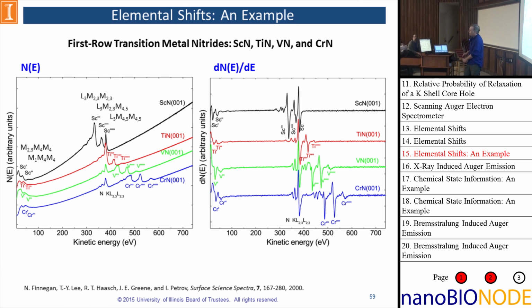Traditionally, Auger spectra can be presented two different ways. The first way is the N of E mode, where you'll see that the lines are fairly small on a linear and intense background. And so in that case, we can also do a first derivative of the spectra. That way we enhance the signal quite a bit and give us a little bit more sensitivity to lower concentration elements.